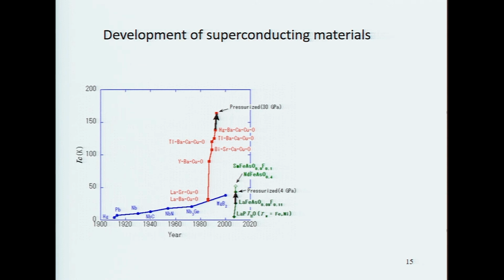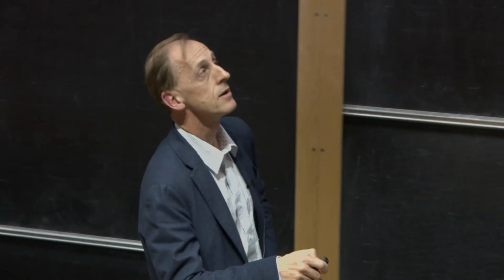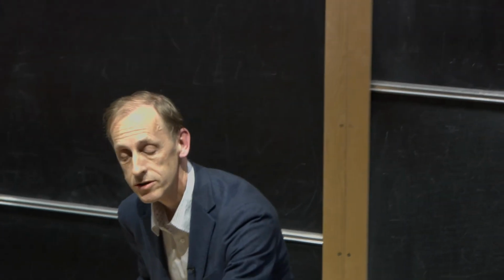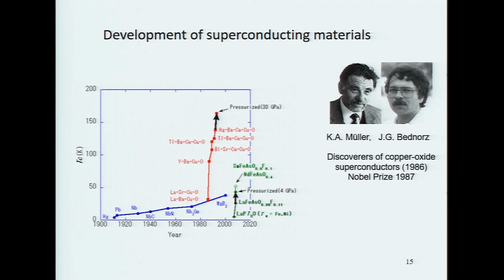A big breakthrough was made in 1986 when Bednorz and Müller discovered this material, which I've been showing you today, which is a ceramic based on copper and oxygen with various other elements. And this actually shot the superconducting transition temperature up to well above 100 Kelvin. In fact, the highest is about 150 Kelvin, but you have to pressurize it to get to that kind of temperature. And there's also been another family discovered in the last 10 years based on iron, which has reached quite high temperatures, around about 50 or 60 Kelvin.